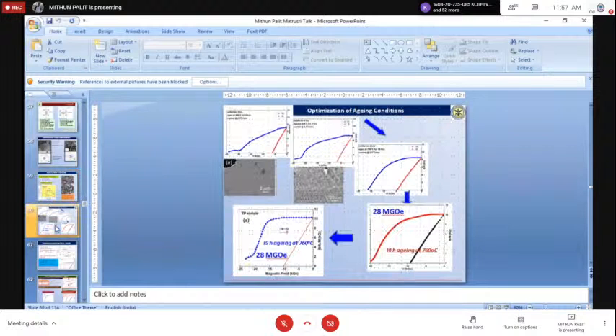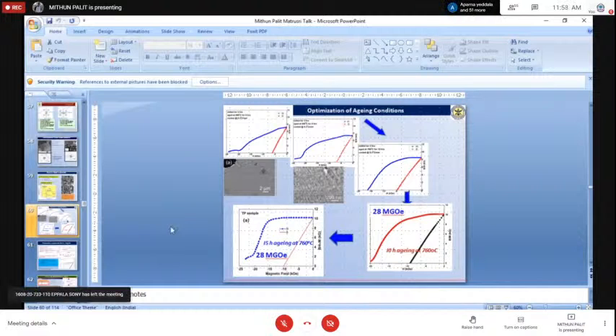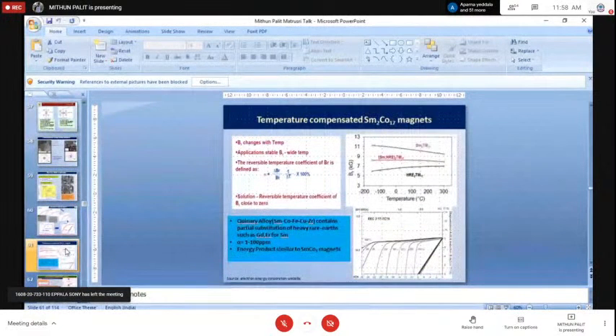You can see from this slide that we have adopted different heat treatments, and you can see in the demagnetization, the second quadrant plot, how the plot shape is changing based on the heat treatment. In the optimized condition, the plot should look like this, which is shown in the bottom left corner. It should have a very square shape and a very linear red color demagnetization curve from the BH loop. Therefore, the heat treatment and the role of precipitate and its distribution is very important.